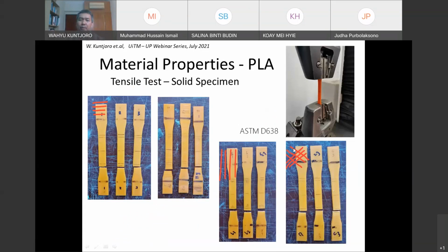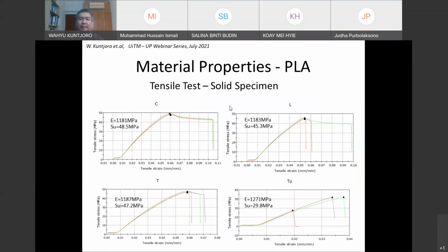And in fact, we also did our own testing using ASTM D638, and again we are able to see that, yes, it is not the same. So for different printing directions, we have different values of ultimate strength, for example. And it is not the same as the ones reported in the article. So over here, for example, we have 48.5 megapascal for this cross direction, and for the transverse vertical direction, it is 29.8 megapascal. So that's quite a big difference.